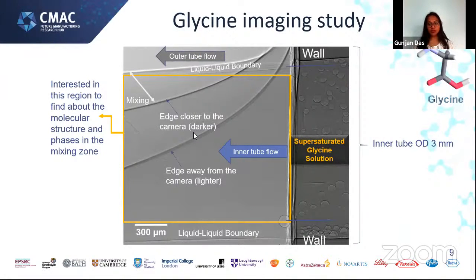So, the glycine imaging study. What we were able to see. This is the inner tubing, as I showed in the previous image. We had the glycine solution flowing through the inner tubing and the antisolvent flowing through the outer. We were able to observe the liquid-liquid boundary, and we were also able to see 3 of these lines. The reason behind this is that the inner tubing was flowing at a much faster rate compared to the outer tubing, which, with gravity, was forcing the outer tubing liquid to move slightly slower and backwards. And also we were taking a 2D projection of a 3D process, leading to these lines being there.